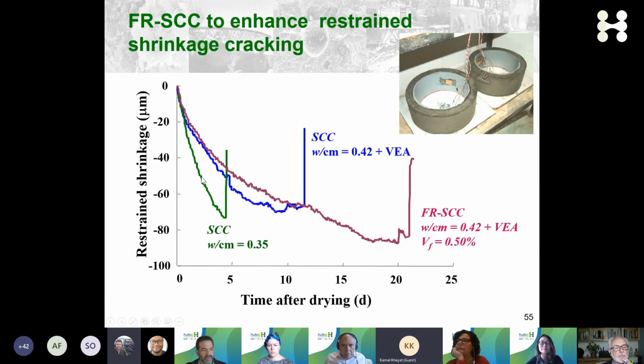And you can design the concrete also to have high resistance to restrained shrinkage by using fibers. And we've been using both synthetic and steel fibers to increase the service life of the repair, double the life, by reducing the restrained shrinkage of the SCC.